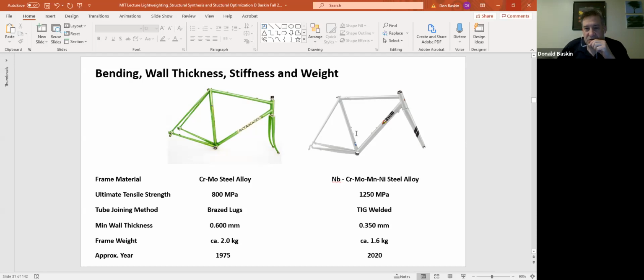Here you see two bicycle frames. On the left is a mid-70s Colnago from Italy. This bike is made out of chrome moly steel. The tubes are brazed together using brass. The ultimate tensile strength of the material from which the frame is made is about 800 megapascals, and the minimum wall thickness up here in the top tube is about 0.6 millimeters or 600 microns. This frame weighs about 2 kilograms, the frame and fork.